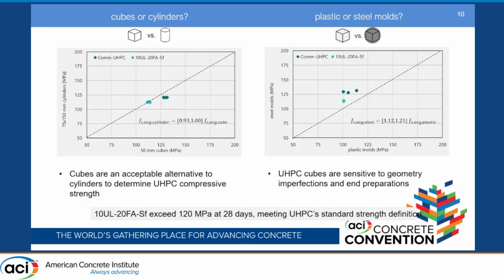And so they are an alternative when you don't have those high load capacity machines to test the strength of UHPC. The other comparison was, because of the number of specimens that we had to test, we used plastic molds. And we compared them with steel molds. And you actually saw that with the more likely brittle behavior that you have with high strength concrete, when you use steel molds, you avoid even minimal geometric imperfection that in this case caused a loss of strength around 15 to 20%. And testing cubes with steel molds, we met the 120 megapascal value at 28 days instead of 91.